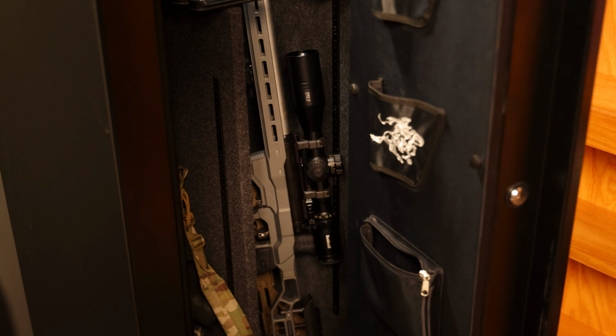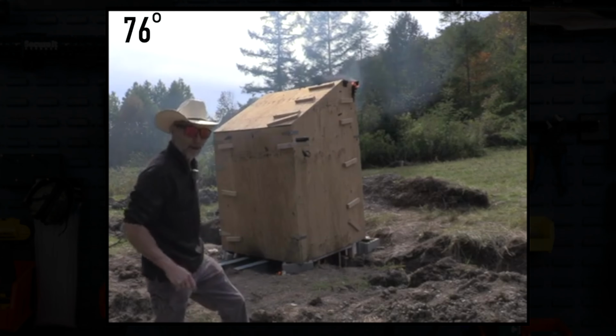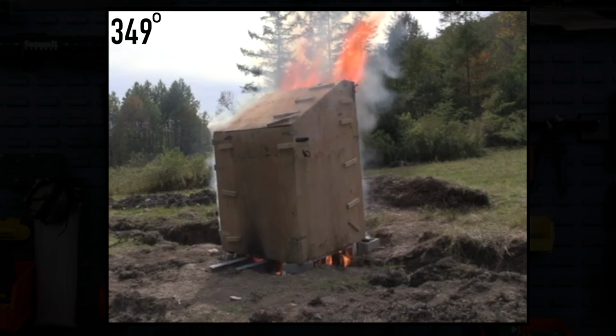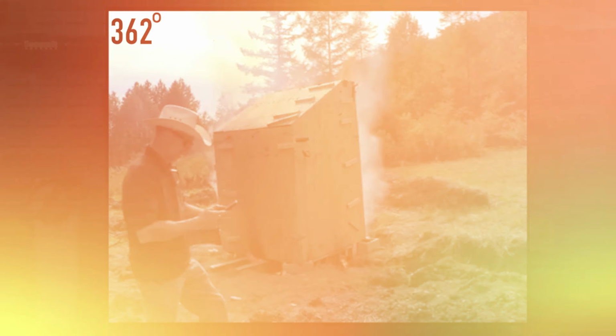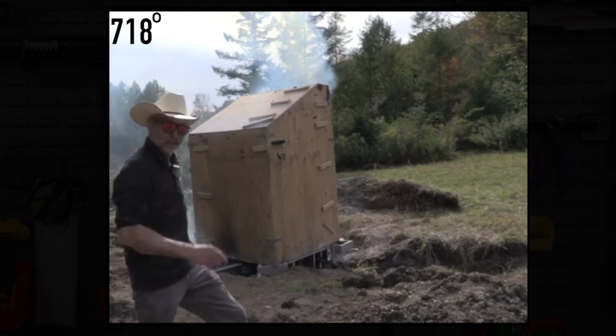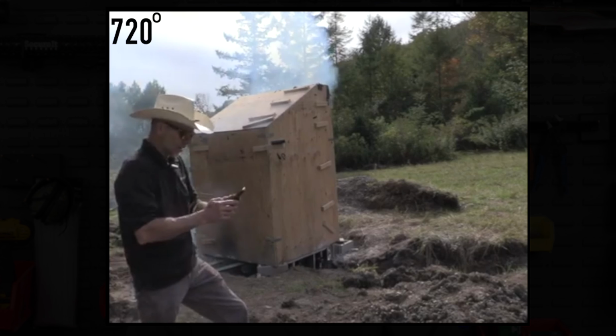And here's one final critical point most people never think about. After a fire, you'll never truly know how hot the inside of your safe actually got. In our real-world fire test, we put the fire out when the safe reached 400 degrees. 20 minutes later, the interior of that safe had climbed to 720 degrees, long after the flames were gone.